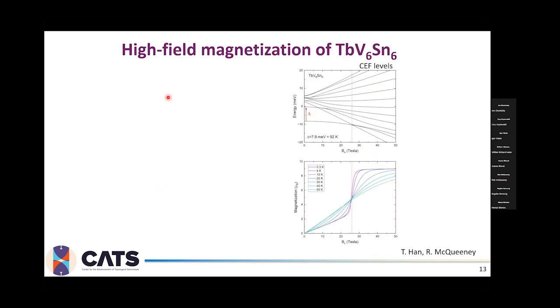So this time, starting again from the theoretical calculation, looking at those levels, we can clearly see that this is a uniaxial doublet ground state. It is very well separated from the excited state by this delta. And the interesting thing happens when we go towards high magnetic field, where this excited state crosses together with the doublet before the doublet is actually splitting. So this is the place where there is a predicted metamagnetic phase transition at around 27 Tesla.